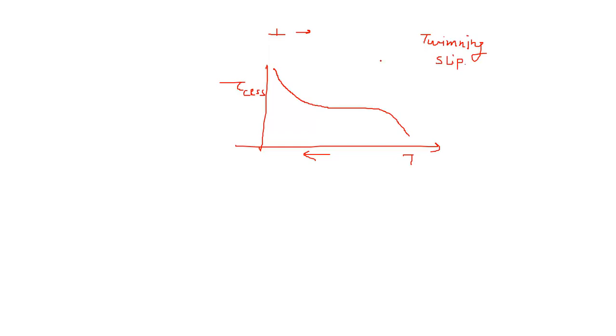So because this tau CRSS is very high, this is the stress required for twinning, which is ideally flat. At any temperature the stress won't change. So this is tau for twinning. Okay, so this is constant. So at a particular temperature tau CRSS is higher for slip than twinning. So the material tries to deform in a twinning manner, and as you go on increasing the temperature, this tau CRSS falls below twinning. Hence now more and more independent slip systems get activated in the material, which homogeneously deform the material.